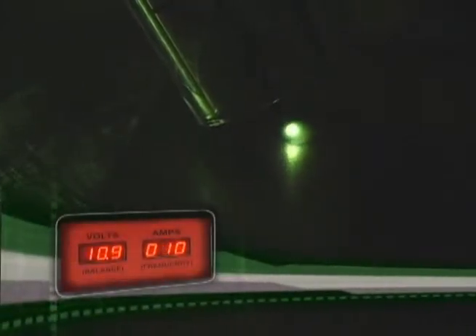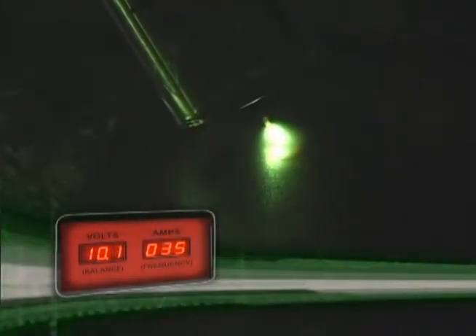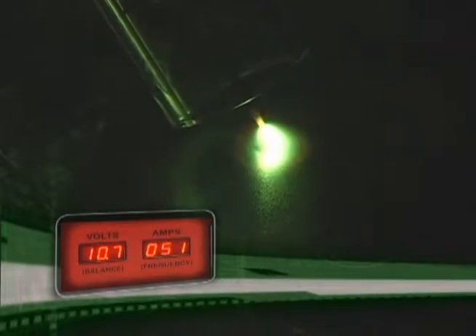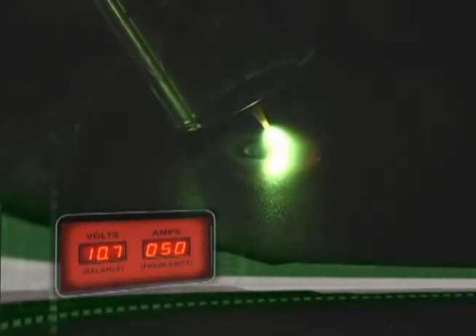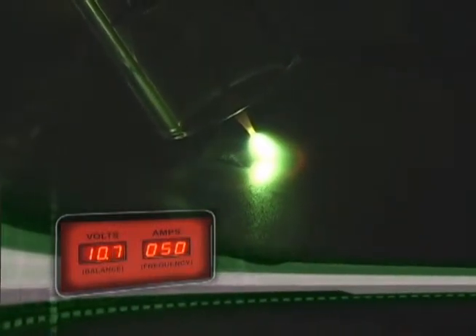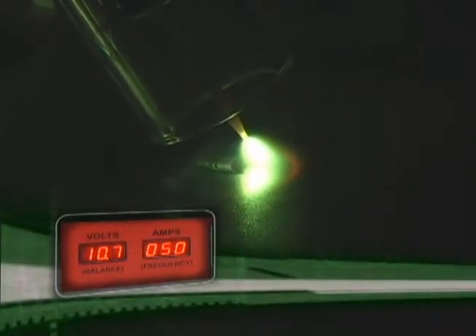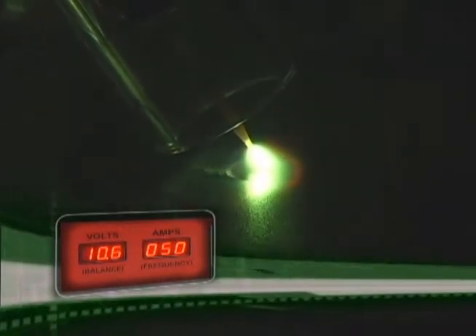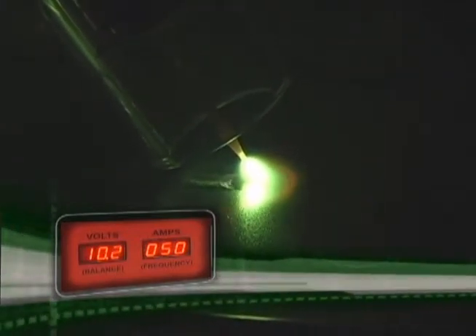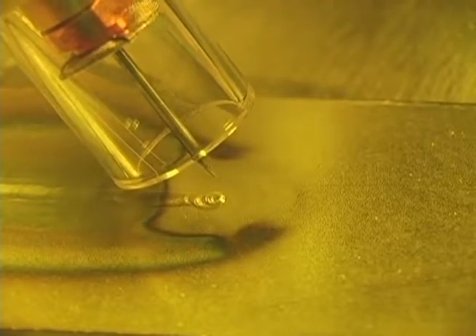TIG welding is all about the puddle and controlling the puddle. You do not start to move the torch until you can see the molten orange puddle. It should be about 1/8 to 3/16 of an inch in diameter. What you are looking for is a constant bead width and being sure you do not touch the tungsten to the work. When you want to stop welding, slowly lift the foot pedal until the arc extinguishes, and remember to leave the torch in the same position until the shield gas stops flowing.